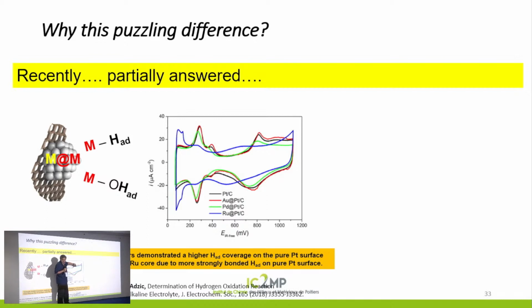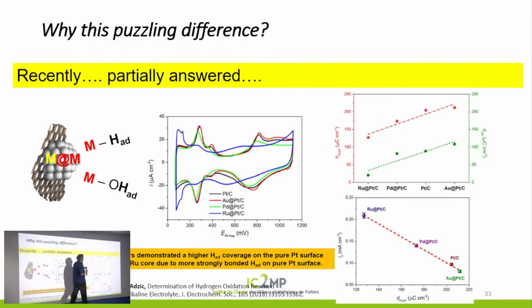And that is the problem of platinum in alkaline, the OH, okay? So, in modifying that, look here, they put ruthenium, platinum, palladium, platinum, gold, and platinum, and they behave differently, and you observe that it's also affected here, as well as here. So the result was that the charge in acid goes in that direction, and in the alkaline, we observe how the amount of OH adsorbed decreases when we have different cores, ruthenium versus palladium versus platinum versus gold. All right? And that shows that there is an electronic effect here induced by the presence of ruthenium atoms inside the core of the particle, and that modifies the electronic effect, and that increases the exchange current density of the reaction.